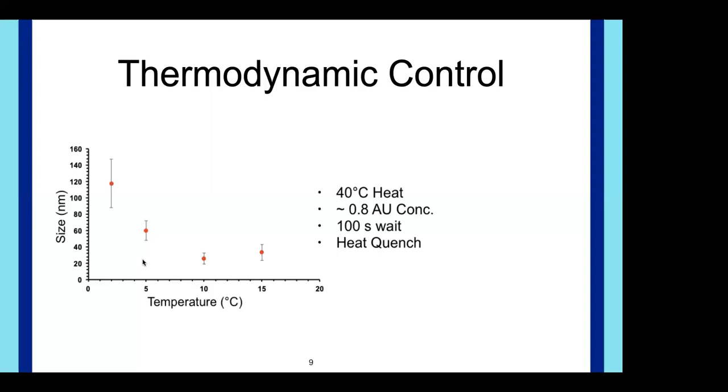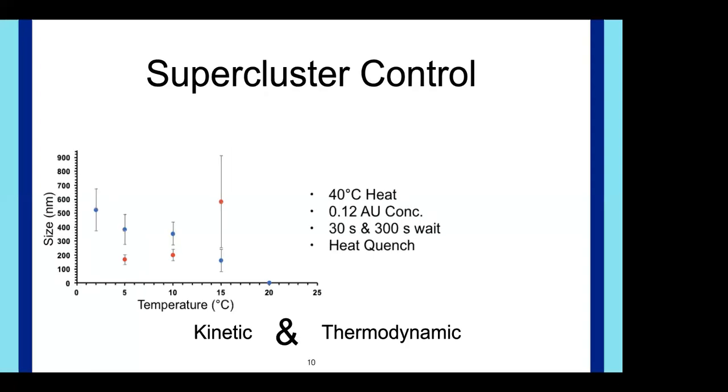Combining kinetic and thermodynamic control is actually fairly simple once you get the concentration of nanocluster solution you're working with worked out. So I did that measurement as well, working with the water bath the same way as before, doing a very quick quench and just a 30-second wait time for the measurement here. 30 seconds was used instead of 2, because every now and then with different concentrations, it would actually take a little bit of time for superclusters to form. If you do a shorter wait time, it might not have already formed yet.